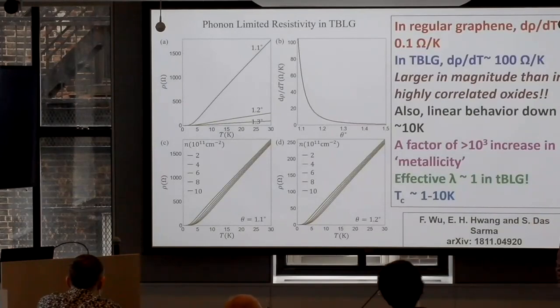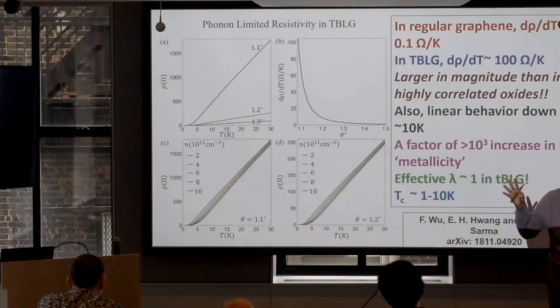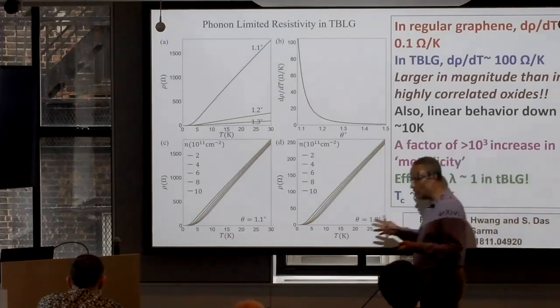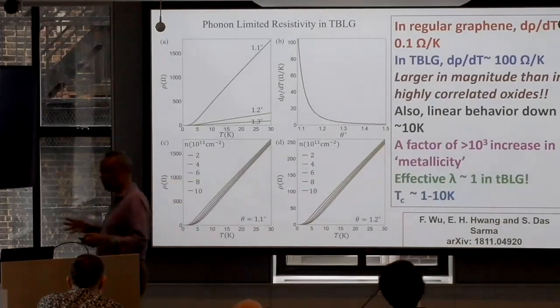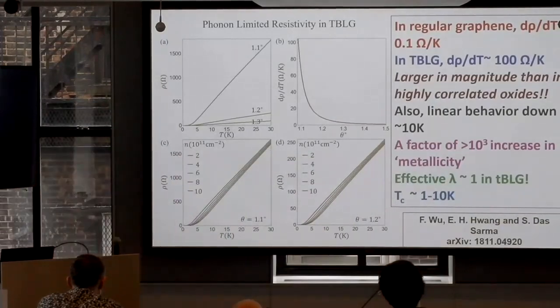Sure, but then there was all this other discussion of phonons associated with twisting and so on. Correct. We have looked into some of those effects. These are some of the things that Andrea and Binghai talked about. We had extensive discussions with them. Some of that physics is included. Main thing is that if, because of zone folding, huge gaps open up in the phonon spectrum, then there will be changes in this theory, but there is no evidence that happens. So it seems that twisting has a strong effect on the electronic spectrum and not such a strong effect on phonons, nor on the electron phonon coupling.